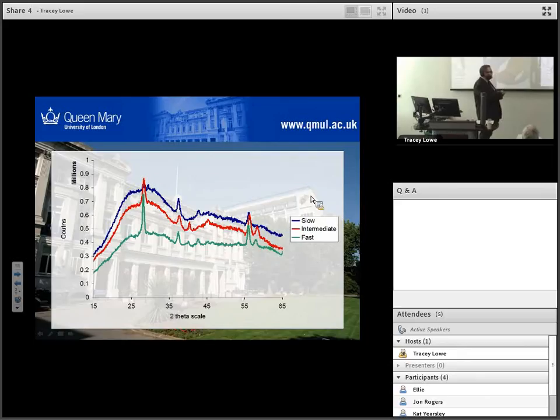You can quite clearly see that some of the relative heights of these peaks is changing. Okay, this is some strain-induced preferential orientation.